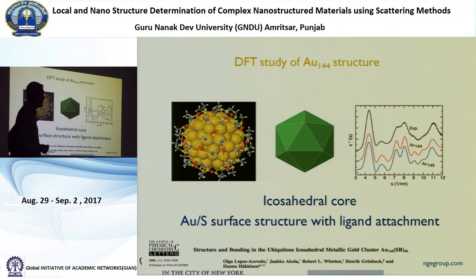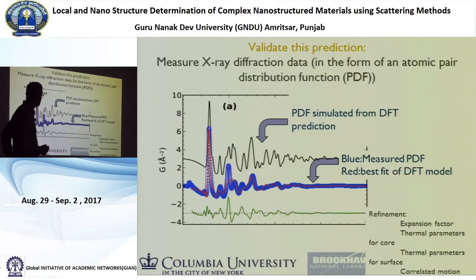Now, because this is such a stable gold cluster, and we could get samples, we could measure PDFs. So we measured PDF. We did this at ESRF, which is a synchrotron in France. And we got this blue curve. And we could compute the PDF from Hannu's predicted structure, and it's that black curve. And it doesn't fit that well, but maybe it just needs to be broadened and smooshed down. So we tried to turn this structure into the blue one here. The red curve is the best that we could do by broadening peaks and so on. And it basically does a terrible job. There's a very strong feature here. It doesn't get right at all. It does a horrible job.